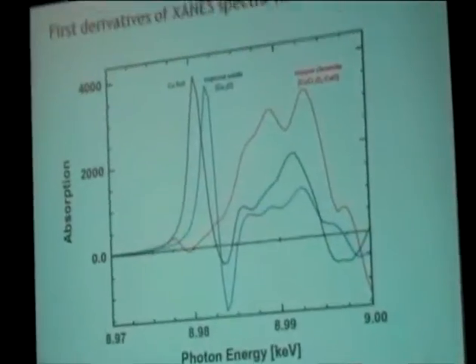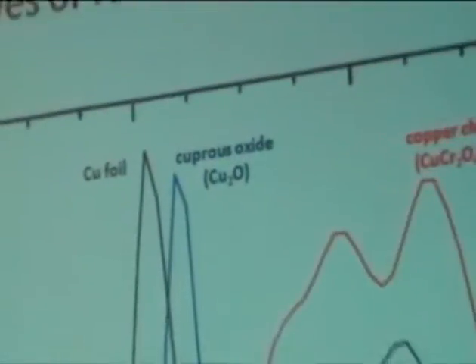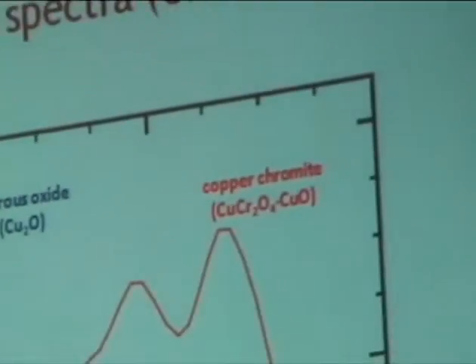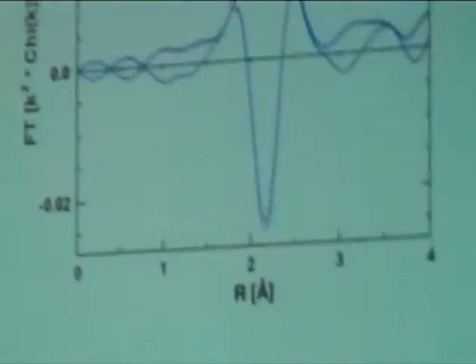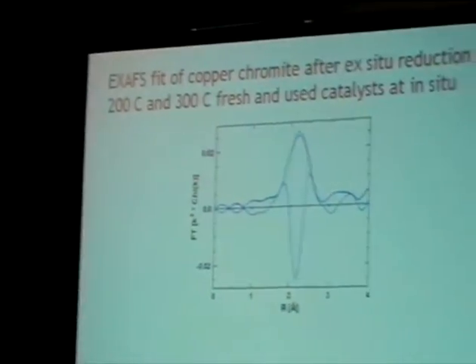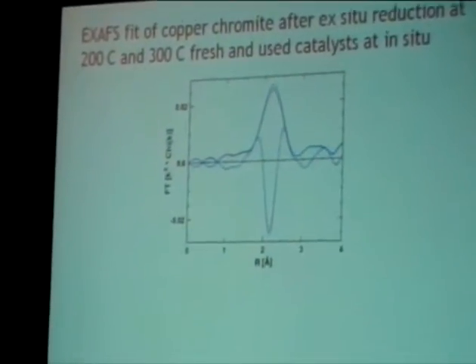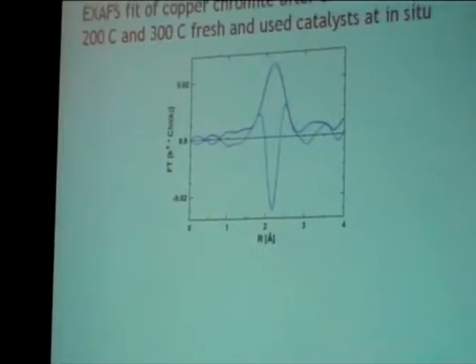This is just some first derivatives of the XANES spectra. We actually use the first derivatives a lot to analyze these because you can see the changes for that. I'll skip over that for lack of time here. Okay, so the XANES tells us a lot about the oxidation state. The EXAFS tells us what things are bound to and the size of the particles that we're dealing with.